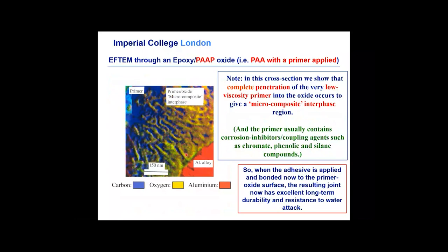Now, the way of avoiding this is to apply a primer. So you can apply a primer, which is a very low viscosity material, usually an epoxy, and usually the opportunity is taken to put in corrosion inhibitors and coupling agents to aid bonding, such as chromates, phenolics and silanes. It's really like a witch's brew in the primer. Now, the primer layer is usually about 100 microns thick, and therefore on this scale the primer layer is off the slide, and then the adhesive layer is applied on top of the primer. But the important aspect is really the primer-oxide interface.